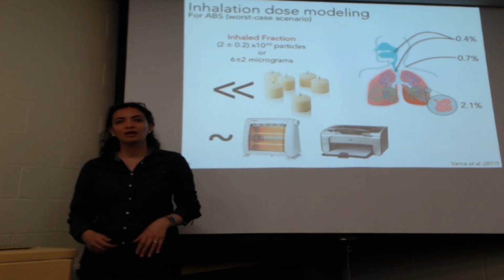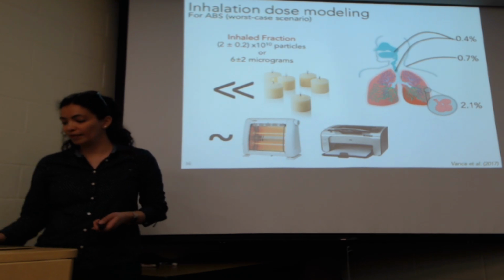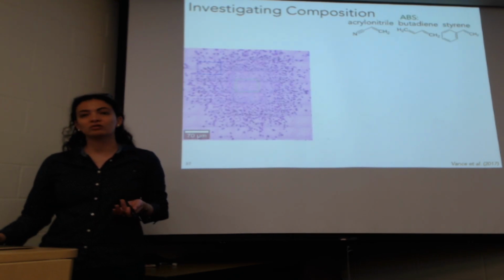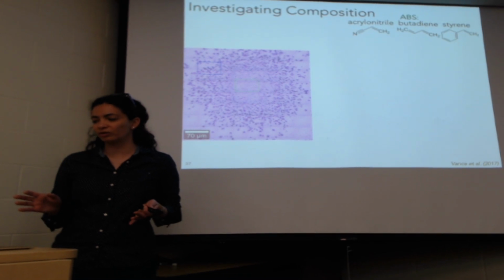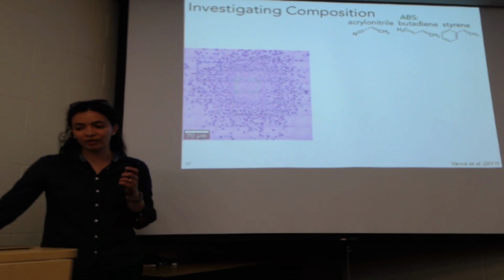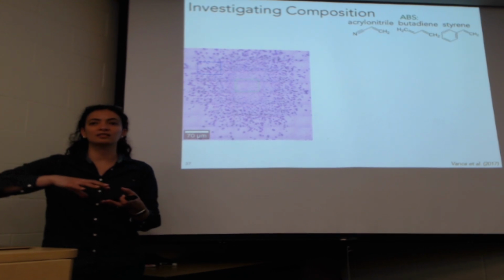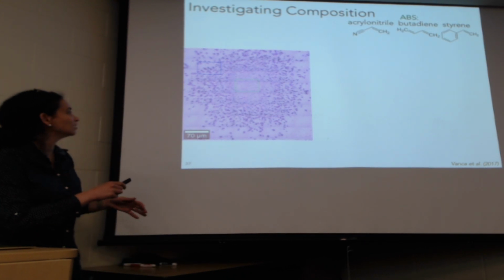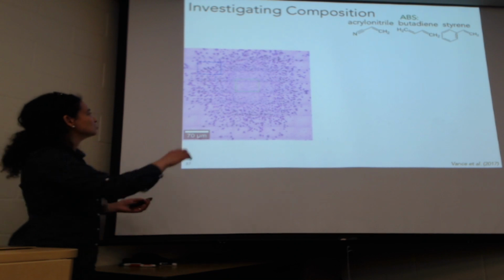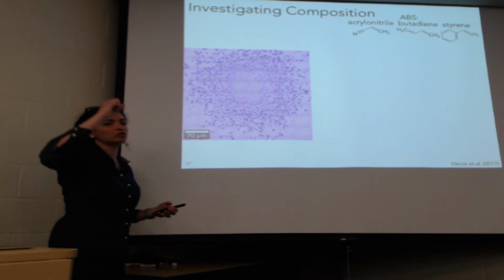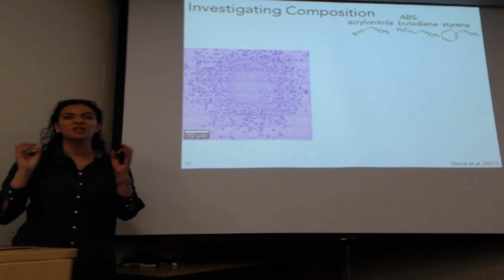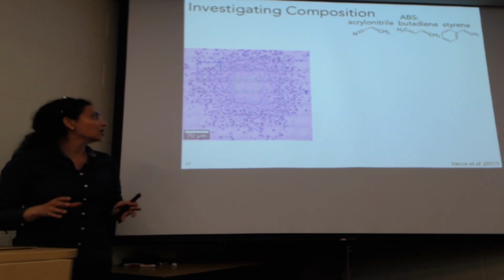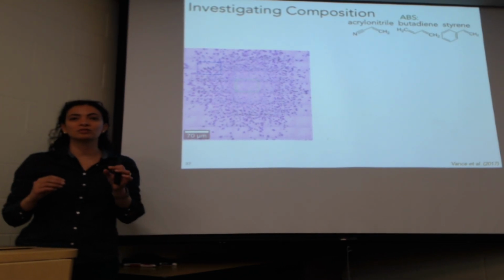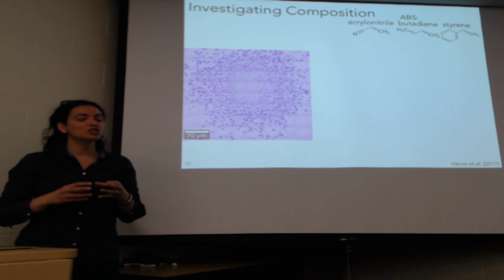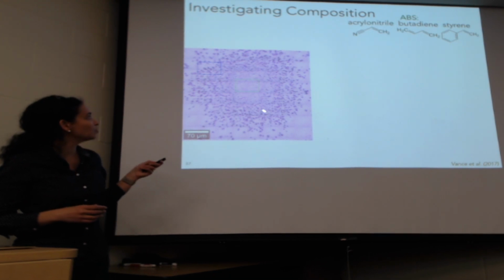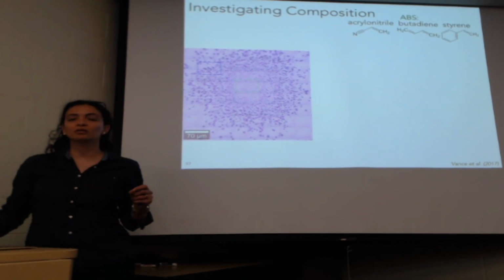Those have also been shown to emit a lot of particles. So we were trying to investigate what the particles are actually made of, and I'll go through this part rather quickly. As I mentioned before, we collected these particles, so we impacted them on this silicon wafer substrate, right? So that's the pink that you see, that's the background. And you can see this splatter image because we were trying to impact as many of these particles as possible, let them accumulate there, get a lot of mass, because as you know, these tiny particles end up amounting to no mass. So we did this for several hours to get as many particles on it as we could, and we took it to something called Raman spectroscopy.